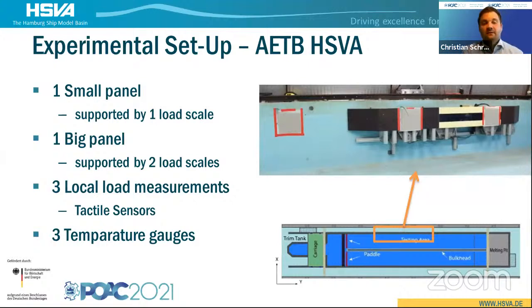How was the experimental setup in our basin to measure the thermal ice pressure? Generally, we had some different panels and some different measuring solutions. First of all, we had one smaller panel connected to one load scale you can see here. And then we had a bigger panel of a 2 meter beam connected to two load scales within the facility. And in addition, we had 3 tactile sensor mats to also derive the local pressures from the thermal ice pressure, as well as to detect possible influences from the measurement setup itself compared to the measurements directly on the basin wall.